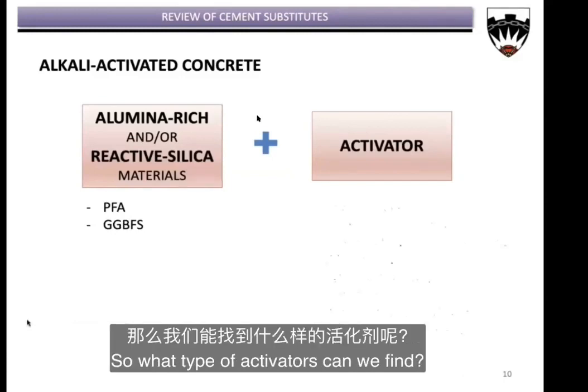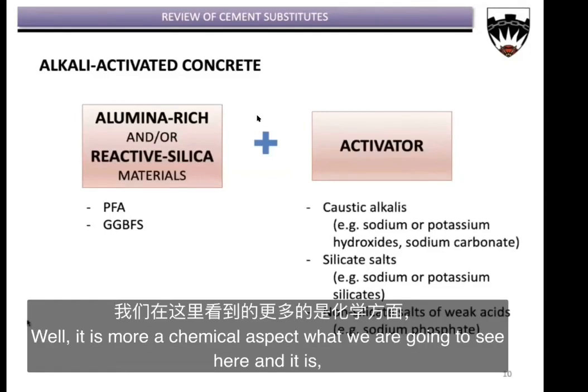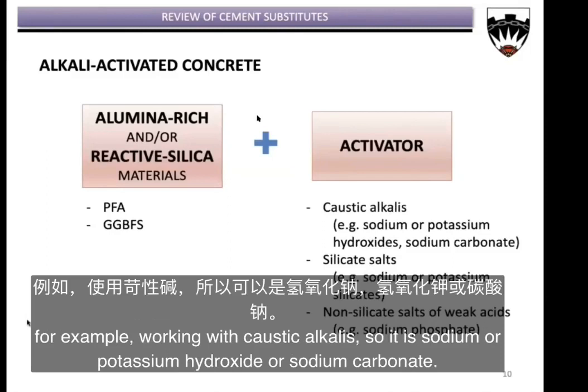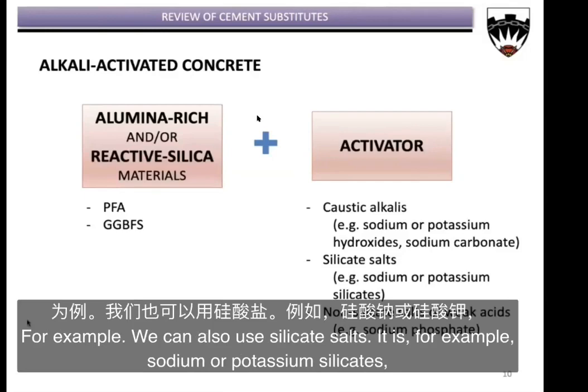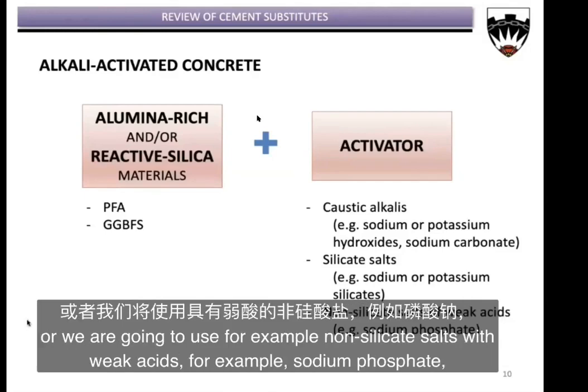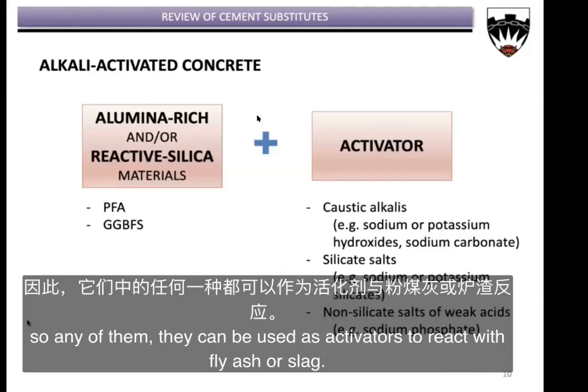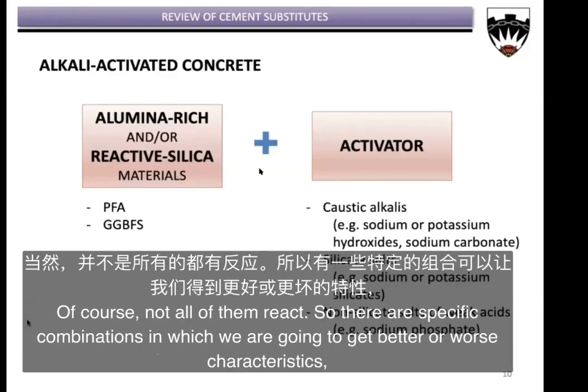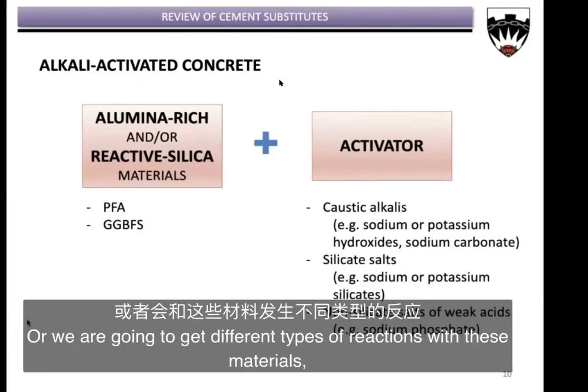So what type of activators can we find? Well, it is more a chemical aspect, what we are going to see here, and it is, for example, working with caustic alkalis. So it is sodium or potassium hydroxides, sodium carbonate, for example. We can also use silicate salts. It is, for example, sodium or potassium silicates, or we are going to use, for example, non-silicate salts, weak acids, for example, sodium phosphate. So any of them can be used as activators to react with fly ash or slag, right? Of course, not all of them react. So there are specific combinations in which we are going to get better or worse characteristics, or we are going to get different types of reactions with these materials, with different performances.